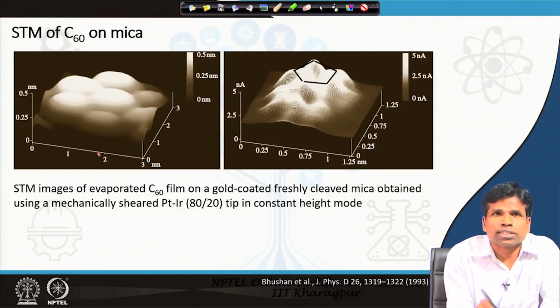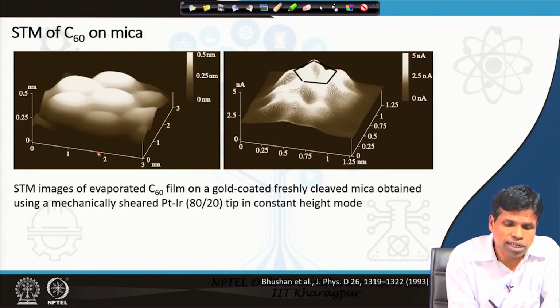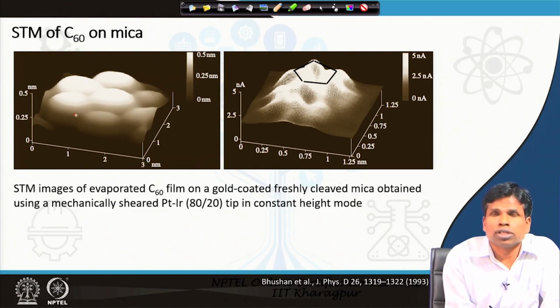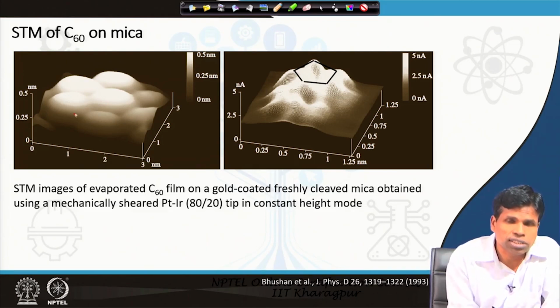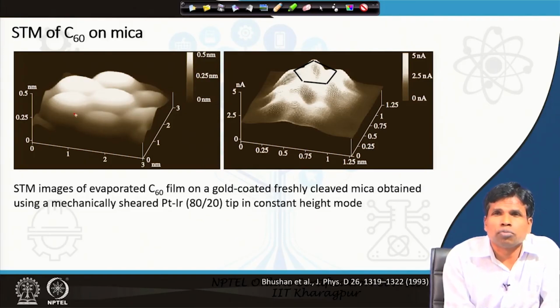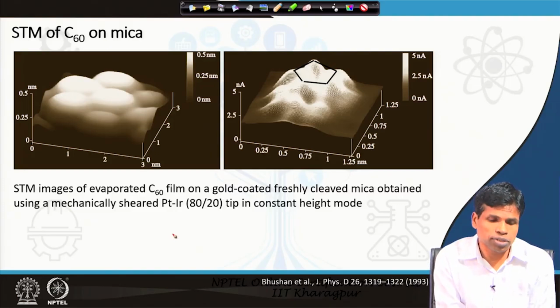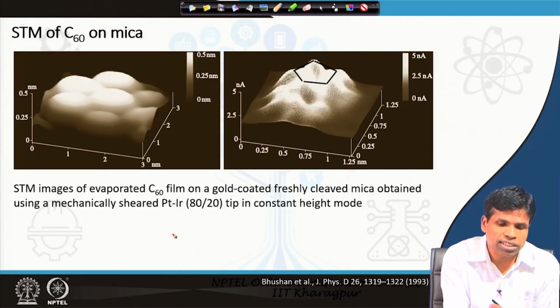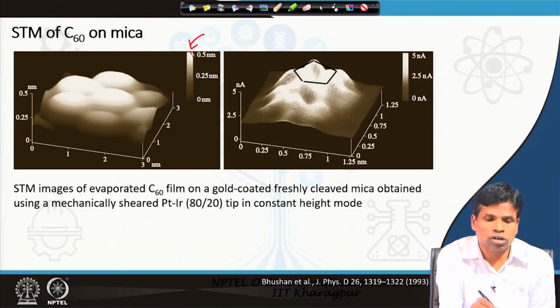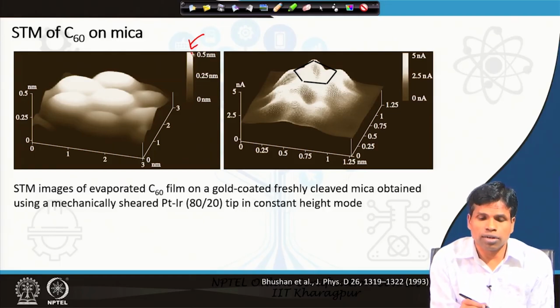And the y axis is giving the lateral direction. From the lateral direction, we can see that the diameter of the fullerene was measured to be 0.7 nanometer or 7 angstrom, which is close to the 0.71 nanometer theoretically expected for the C60. And in the height case, you can also see this scale bar telling about the height of the sphere, or in this case the fullerene molecule.